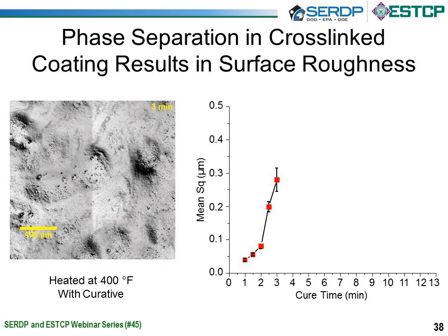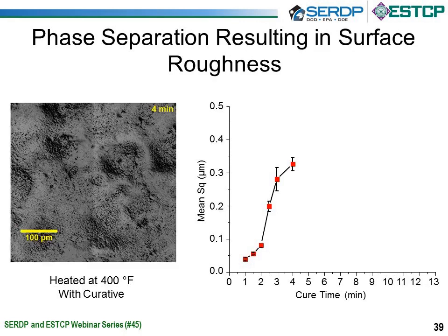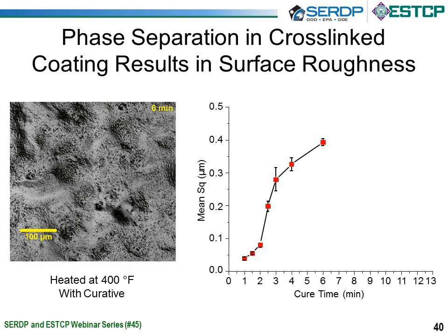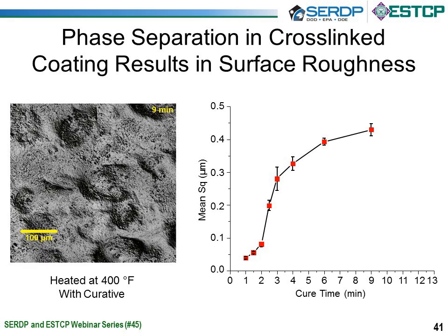Just quickly flipping through slide 39, you can see as we continue to heat at 4 minutes, the surface roughness increases, albeit at a lower rate. And slide 40, at 6 minutes, we've progressively increased the roughness. And we will increase the roughness, as you'll see in slide 41 now, up till 9 minutes. We believe that this increased roughness results from the continued reaction and the continued phase separation that's occurred.